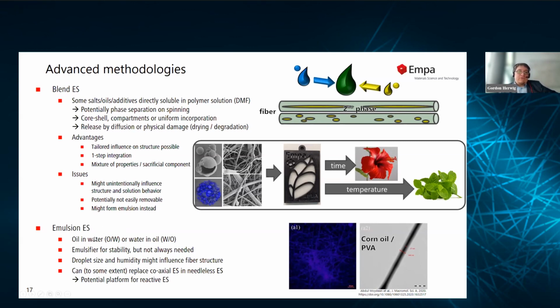For emulsion electrospinning directly, there are different ways, for example, with oil and water or water and oil options. There's a nice example where they used PVA and corn oil to encapsulate that inside. You can use emulsifiers, you don't have to. There are different options to play around with droplet size and humidity, and the effect that has on the electrospinning. The good thing is it basically replaces to some extent coaxial electrospinning in needleless electrospinning. So with needleless, you can do this all in one go without coaxial electrospinning, but of course you don't have that nice control over it. Whereas with coaxial you get nice core-sheath structures, you might not get that with needleless electrospinning.